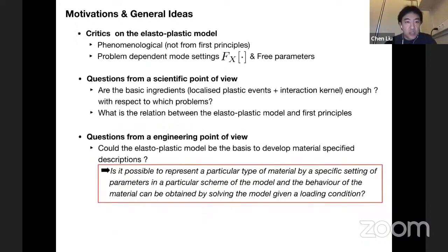So this is also reasonably captured by the model. But on the other hand, we have some critiques on the elastoplastic model. So the major one is that the elastoplastic model is quite phenomenological. We don't know how to derive these things from the first principle. And also with respect to each problem, for example, in the slides that I showed before, we changed the settings of the closure, and we changed the parameters to fit the different phenomena. So people can criticize that it just reproduces what happens in real life, but that doesn't make progress in understanding.